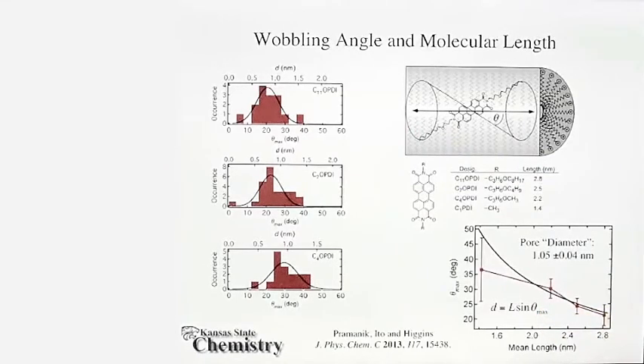We can also determine the ensemble average cavity diameter, and we've done so down here with this plot. The value obtained is just over one nanometer.